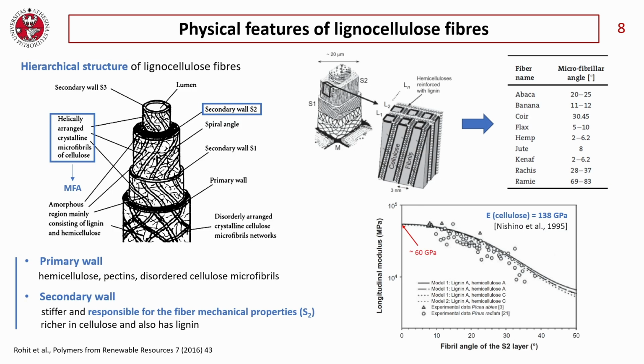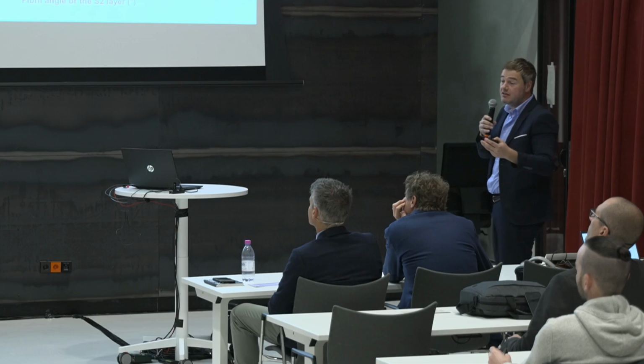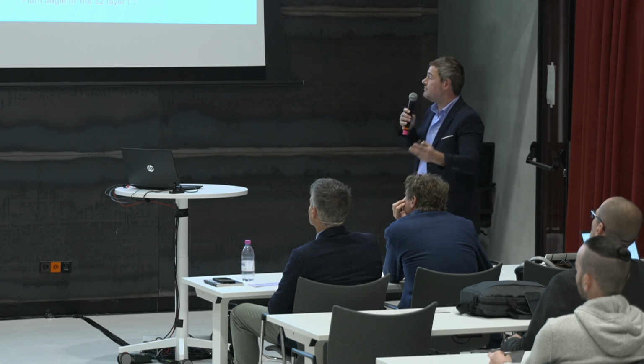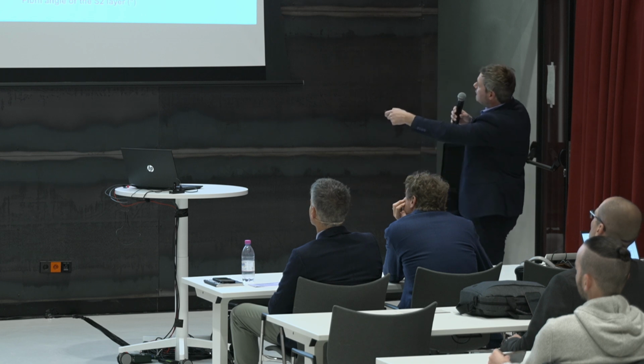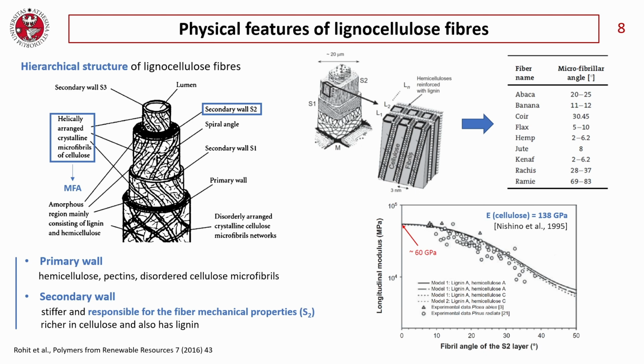Going more into detail, you can see that the secondary wall, which is responsible for the mechanical properties, has helically arranged crystalline microfibrils of cellulose. The angle formed by these cellulose fibrils with respect to the longitudinal axis is known as the microfibrillar angle and determines the stiffness and the strength of this fiber. In particular, from this graph, you can see that by increasing the fibril angle, you decrease the elastic modulus and the mechanical properties of the fiber.